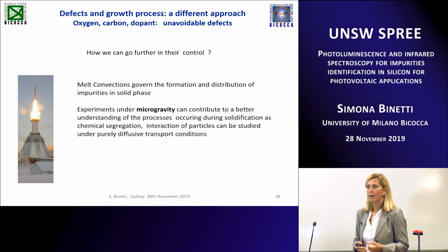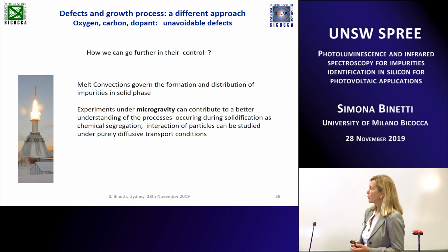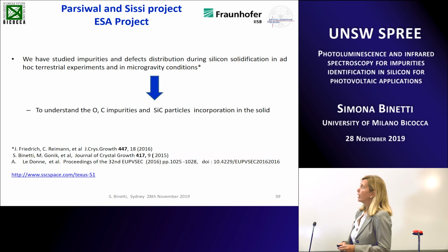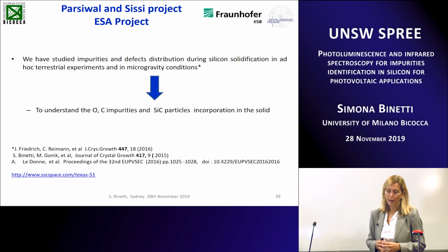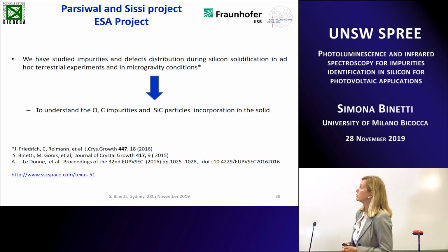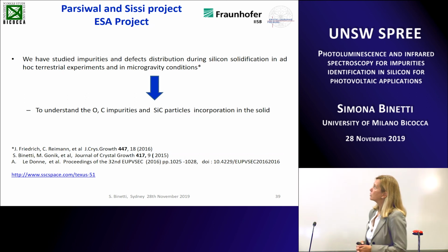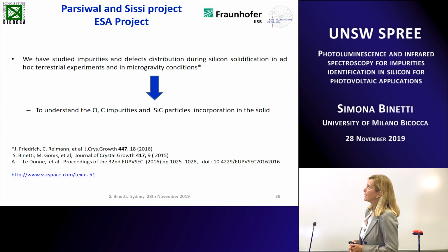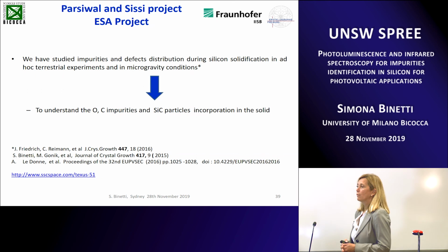But if you perform experiments under microgravity conditions, this process can be studied only under pure diffusive transport conditions, and so it's a completely different perspective. So, in the frame of a European project that was partially supported by the European Space Agency, in collaboration with Fraunhofer of Stuttgart and also with Freiburg, the Institute of Crystal Growth Material, we tried to understand, in some ad hoc growth processes and also in a microgravity condition process, the incorporation of oxygen and carbon and of silicon carbide in the solid ingot.